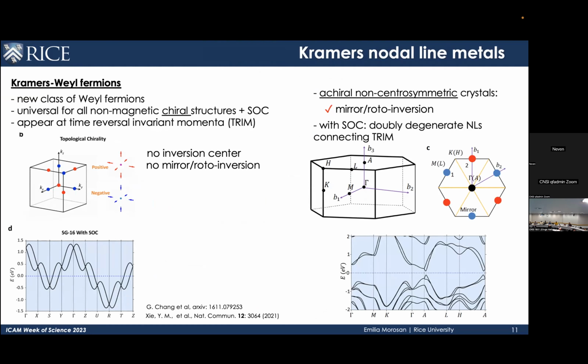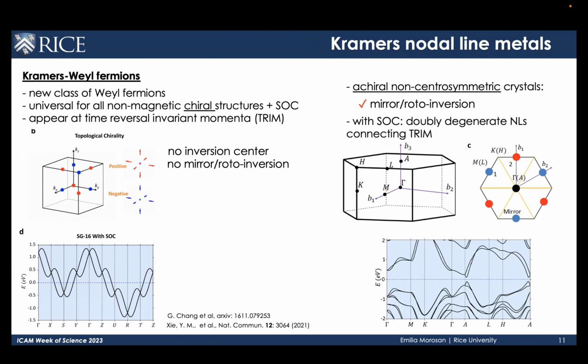Okay, so these Kramers-Weyl fermions are predicted theoretically to be a universal feature in chiral structures with spin-orbit coupling. And what they are, they're these degenerate points that are pinned at high symmetry points in the Brillouin zone, as I'm illustrating here schematically. If we now move to achiral crystal structures with spin-orbit coupling, these Kramers-Weyl fermions become degenerate nodal lines. For example, over here between the gamma and A points in the Brillouin zone, you see these lines are degenerate, and then they are non-degenerate away from that particular line in the Brillouin zone. And so what they are, these Kramers nodal lines are doubly degenerate lines connecting these time reversal invariant momenta, these high symmetry points in the reciprocal space.